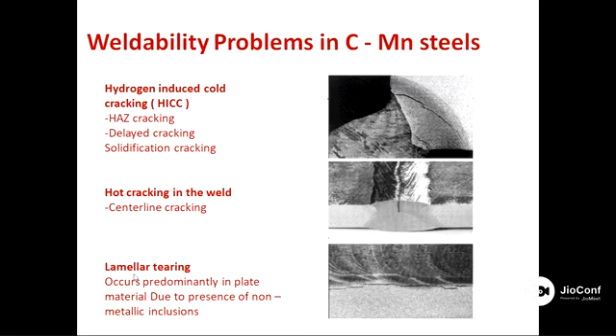Then there's lamellar tearing. This is a new word for you, but lamellar tearing is because of the presence of non-metallic inclusions. Because during the steel making practice, some inclusions are developed. There are oxide inclusions, nitride inclusions, sulfide inclusions. So whenever these inclusions are present in a rolled steel structure, right, a hot rolled structure, and when you perform welding, you will end up with cracking, and there is lamellar tearing, right?